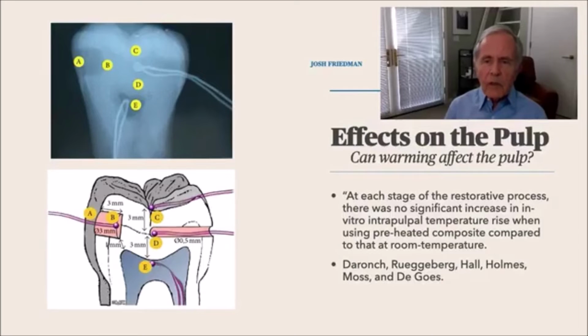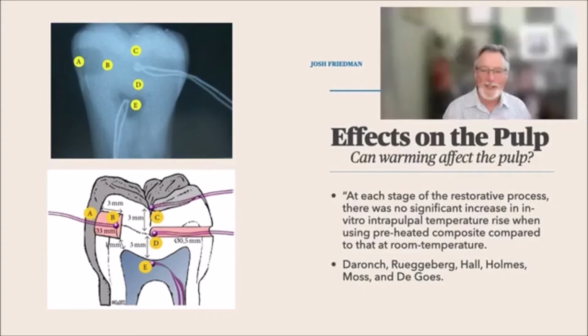So some people have asked the question, what effect would heated composite have on the dental pulp? Again, this was studied and looked at in detail. The picture on the left shows the thermocouples placed at different locations on the tooth. What they found was essentially no significant increase, a very minor increase. The greatest increase was with the heat generated by the curing light that polymerizes the material. Even LED lights put out a lot of heat. If you doubt that, you could just try putting it on your fingernail for 5 or 10 seconds and see how it feels. Thanks, Josh.